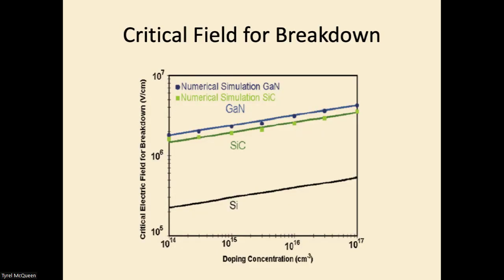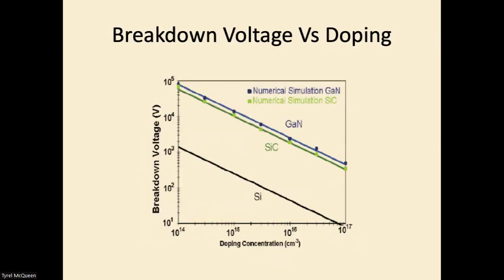But notice the dramatic difference between the critical field of silicon carbide and the critical field of silicon. There is a lesser difference between that and gallium nitride, and this is a matter up for question. This is an old viewfoil, so people may say there's more change here. But the takeaway point is we had a dramatic change in the critical field of silicon carbide versus silicon. Once you know the critical field, then you can predict the breakdown voltage versus doping. Here is that calculation for silicon, and here is that calculation for silicon carbide. This becomes the basis for why these two materials and others like gallium oxide become so important when you go to the higher breakdown voltages.